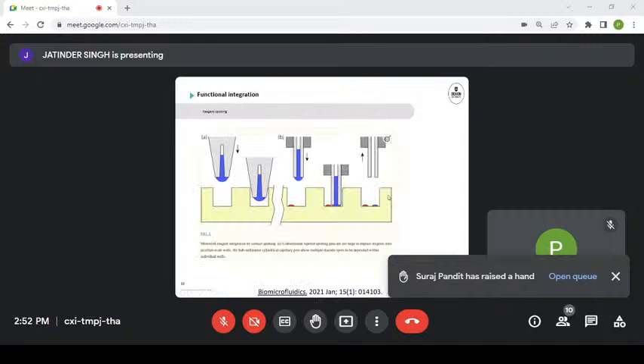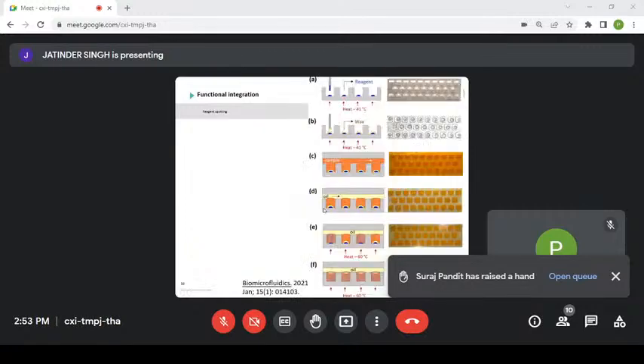If we talk in a little bit more detail about reagent introduction, if we want to deposit them on a small area, it may be smarter to have a straight nozzle where it's coming down than a conical one, because that allows putting two reagents in a single reservoir. And here, this is the picture that I was talking about earlier, where they deposited the reagents. Initially, with a hot needle, deposited some wax on top. Could add the sample, do some other fluidic processing, maybe some sample handling.